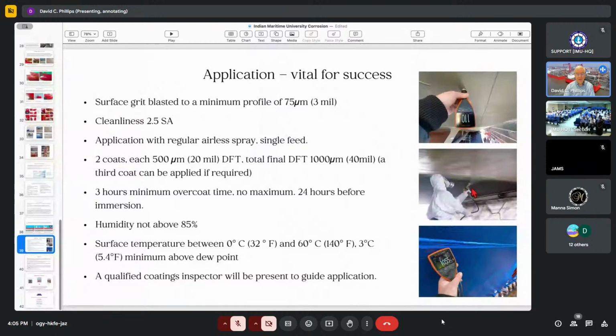The other side of it is that you don't have to put it on after 3 hours. You can wait 3 days. You can wait 3 weeks. This is very handy when you're new building a ship, because usually the ship is constructed in blocks, and they can be at different shipyards, and then taken to a dry dock to assemble. And then the joints are welded up and the ship is finished.